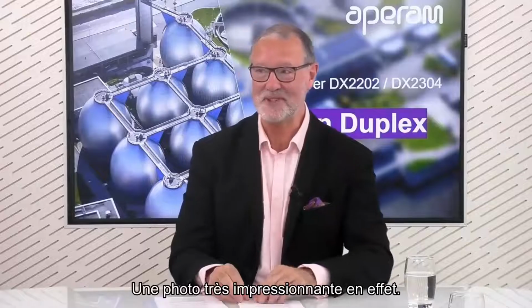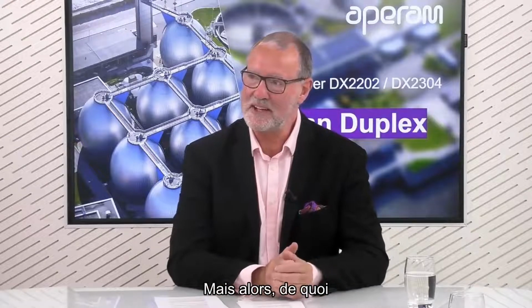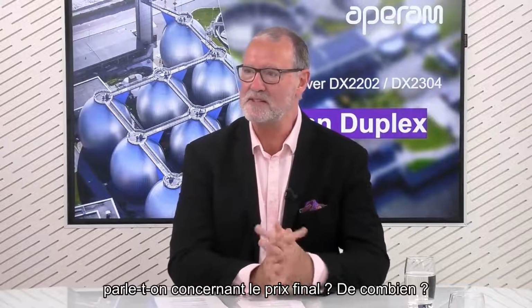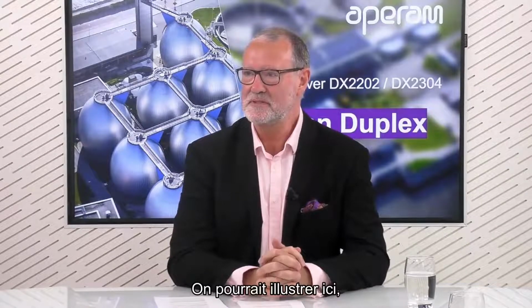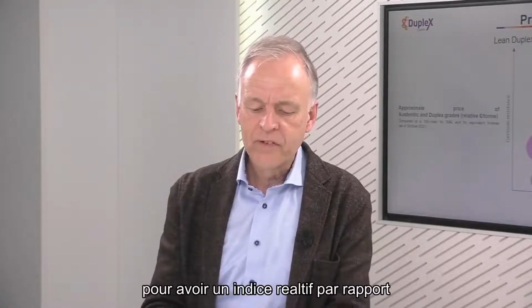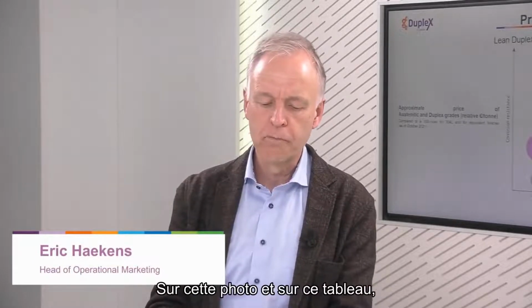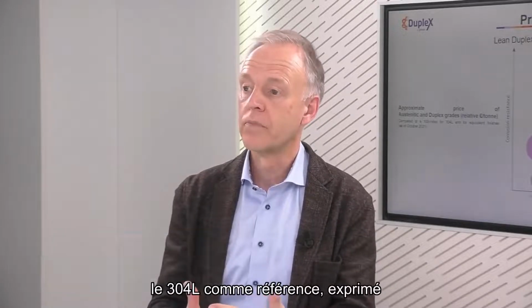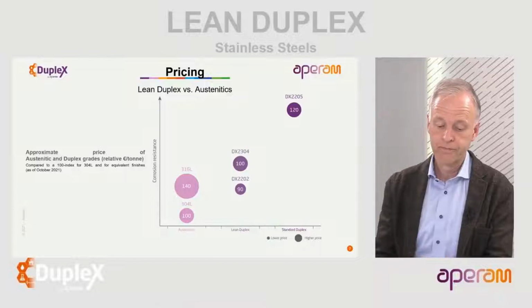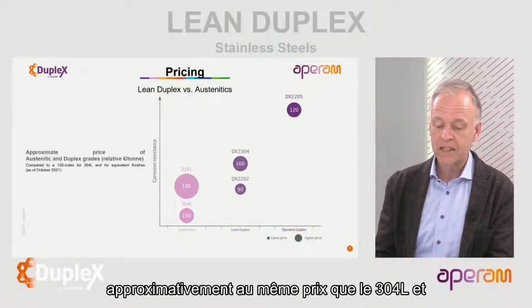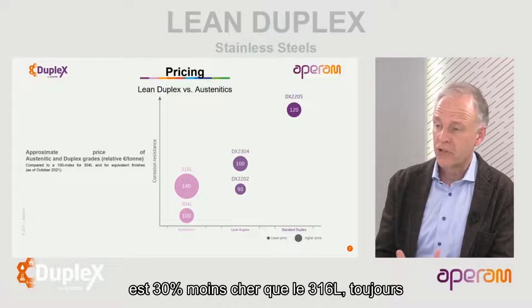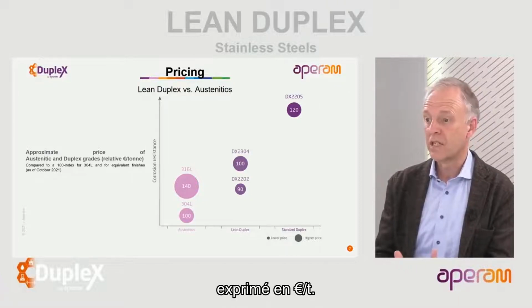Very impressive picture indeed. Can I press you a little bit? What are we talking about in terms of final price? How much? Well, there we could illustrate a relative index compared to standard grades 304L and 316. So on the table, you see a relative index of 100 for 304L as a reference, expressed in euro per ton. You see clearly that the lean duplex is about the same price as a 304L, and that it's 30% cheaper than a 316L, again expressed in euro per ton.